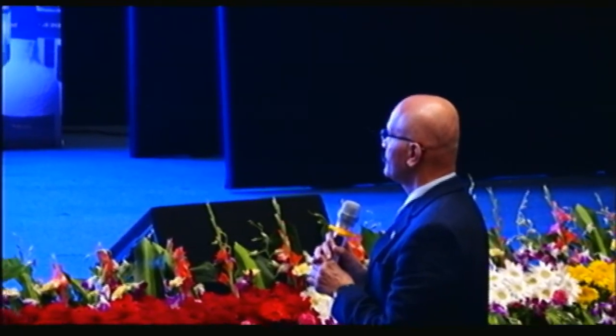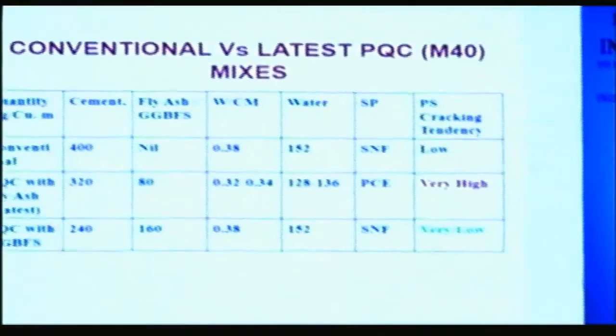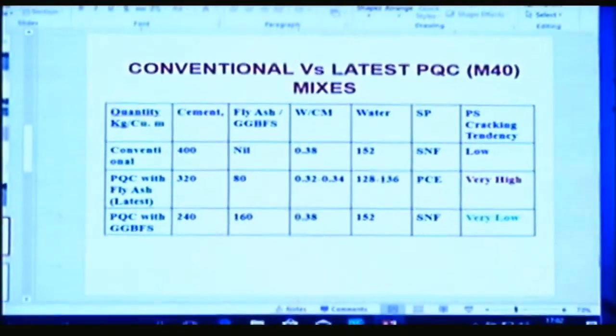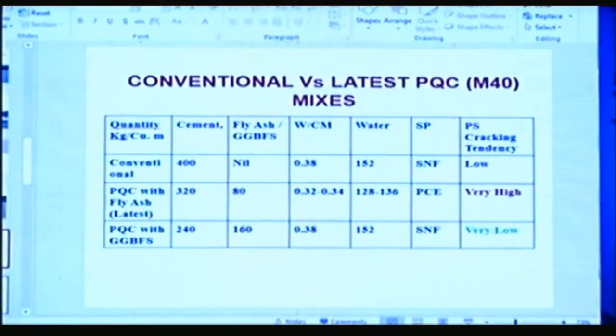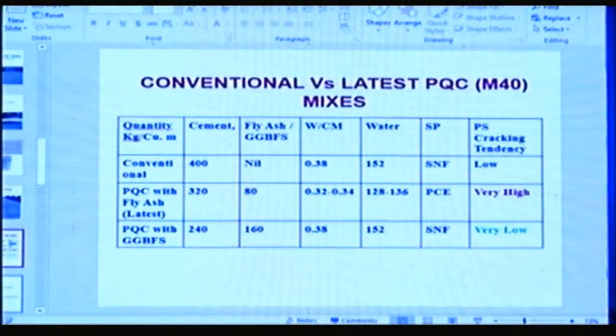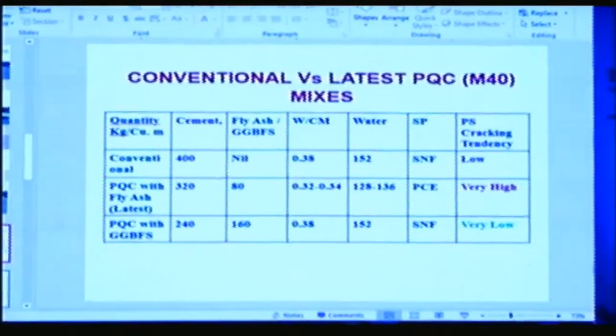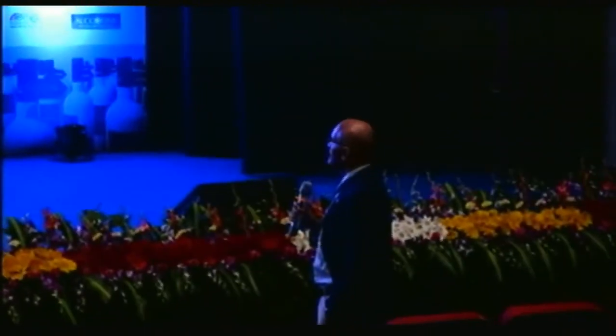Yeah. When PQC with fly ash, what do you mix? Normal mix has superplasticizers, 400 kg cement, 0.38 water cement ratio. When you replace cement with fly ash, you come down to 320 kg cement plus 80 kg fly ash. But to achieve the same 7 days or 28 days strength, you have to lower the water cement ratio. So you come to 0.32 to 0.34, and you have to use PCE based superplasticizer, because only PCE based can give you workability at that lower water cement ratio. And if water is very less in your mix, your tendency of plastic shrinkage cracking will be very high, because the rate of bleeding will be very low and rate of evaporation will be too high.